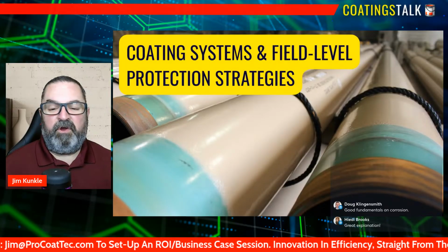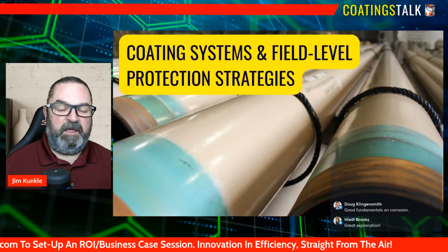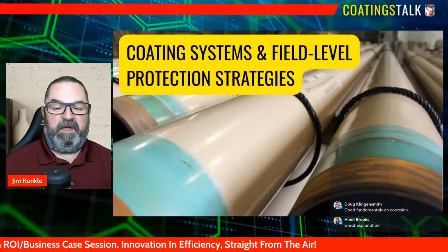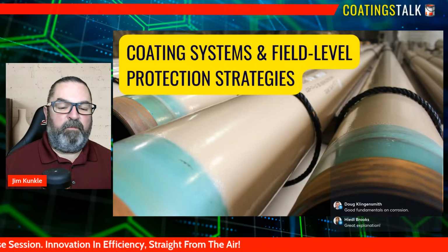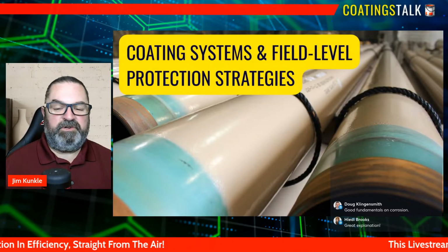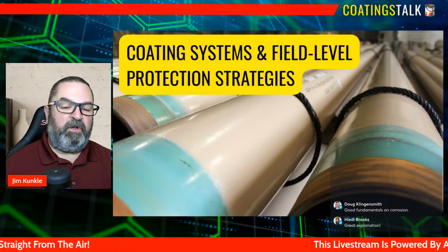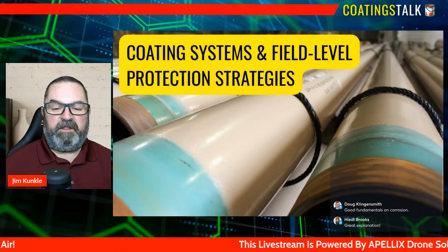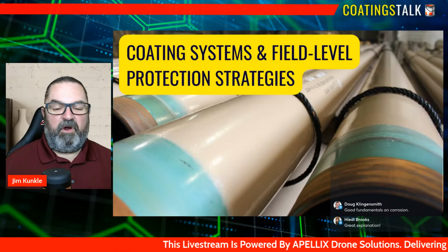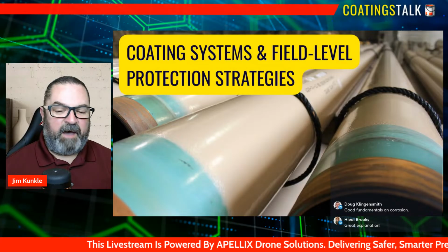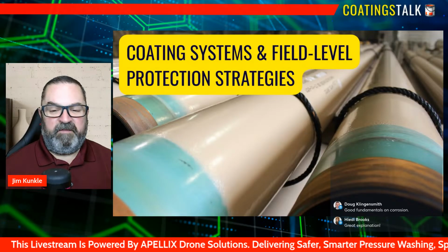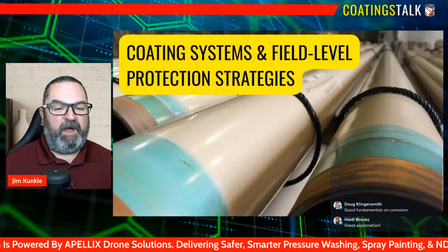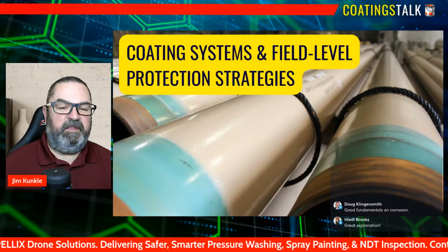And when the barrier is intact and properly applied, the metal underneath remains isolated from the corrosive elements that would otherwise trigger uniform corrosion, galvanic reactions, or localized attack. This is why surface preparation and film thickness are so critical. Any gap, thin spot, or defect becomes a direct pathway for corrosion to begin.